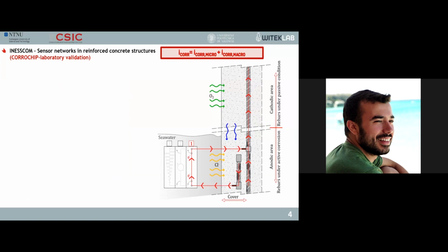On this basis, the research group in which I am involved designed a sensor that remains electrically connected to the rebars and takes part in the existing macro-cell currents. When we want to measure corrosion, there are two measurement positions. The first one is for measuring the macrocell current, and the second one is to measure the microcell corrosion current using the technique described previously by my colleagues. In this way it is possible to know the total corrosion of the sensor, which in this case is representative of the closest rebar where the sensor is located.